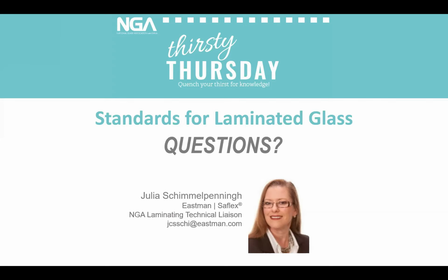Okay. We have just two more questions and then we will conclude the day. Is it possible to have different readings from each side of the interlayer? Absolutely. That's why you rate both sides. There are interlayers that are very sensitive to the glass orientation. There are interlayers that, if you think about processes, they can pick up some contaminants. If you happen to store them with something that's not compatible, you can have an adhesion on one side and a different adhesion on the other side.